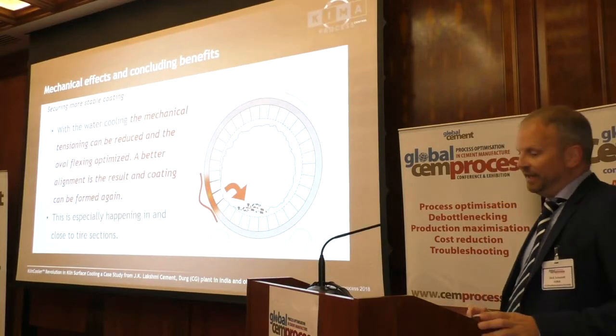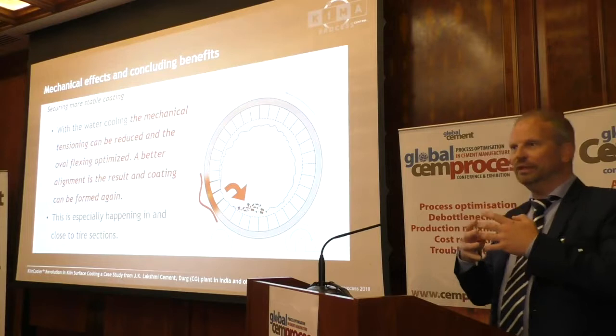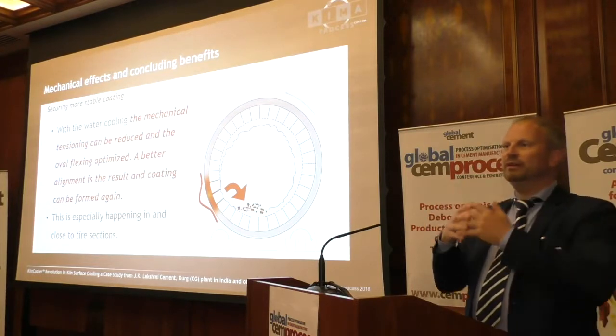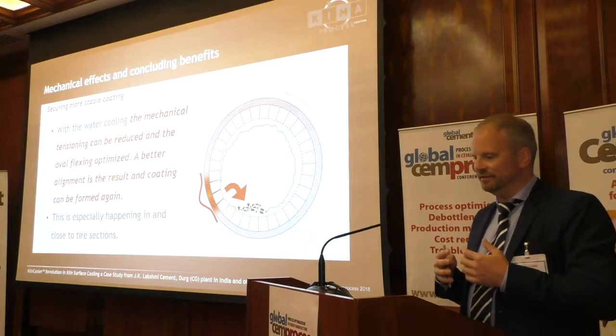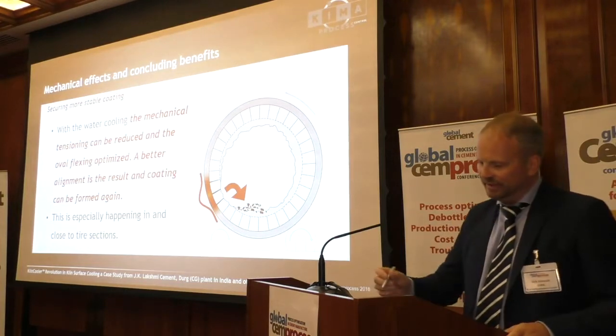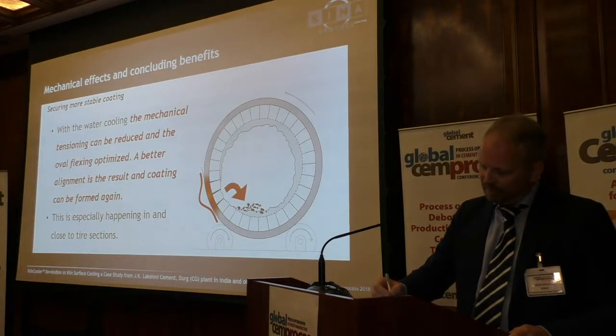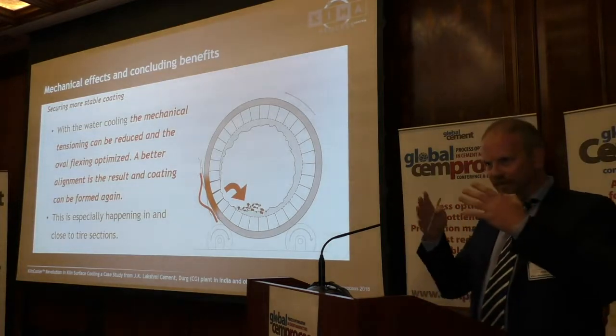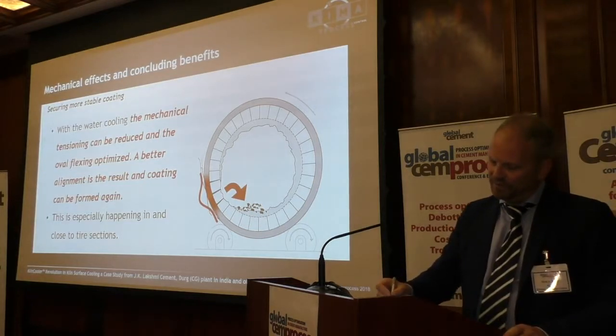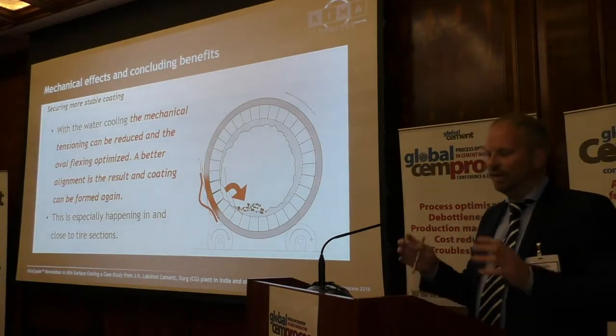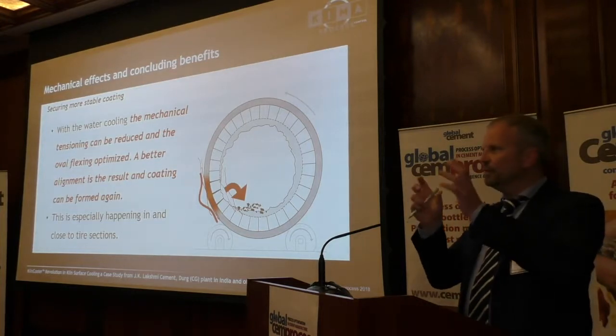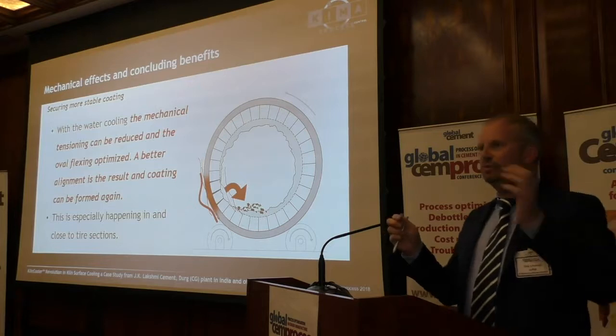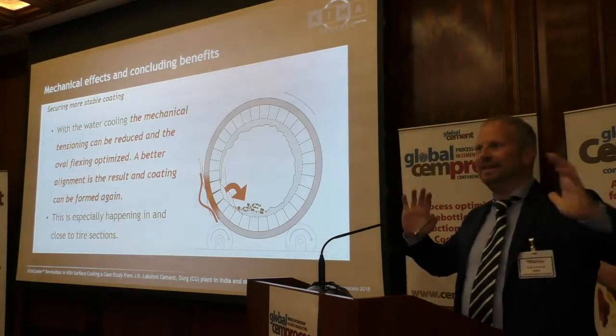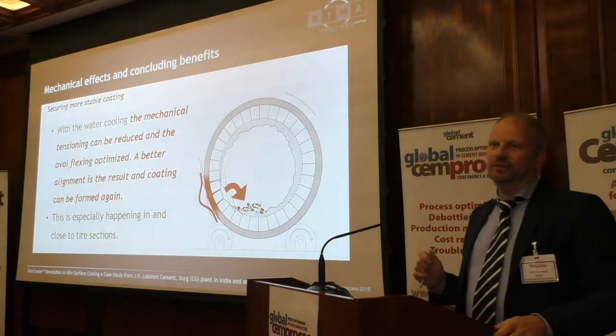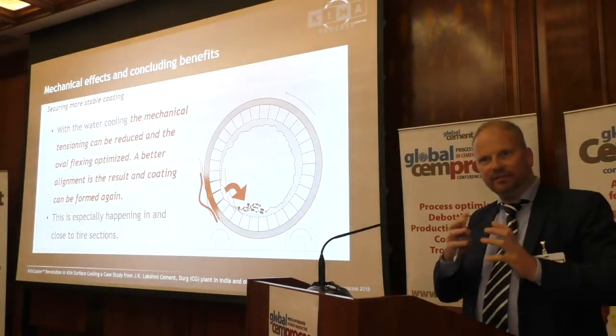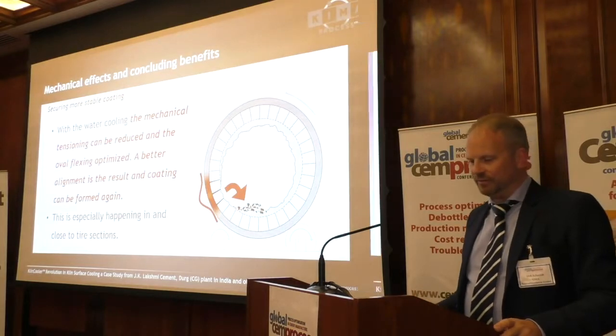So the mechanical tensioning that you usually have when this hotspot is there will be compensated, nothing else. I show it to you here. When you bring this bubble, this expansion of steel, back into place, you will have a more stable situation. When this steel expands, the bricks become loose. When the steel is cooled from outside, it shrinks. So it is like a clamp for the bricks. So you have more stable bricks again, and that gives the opportunity for new coating formation.